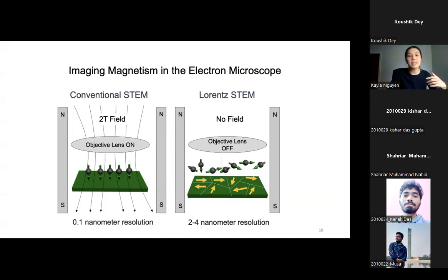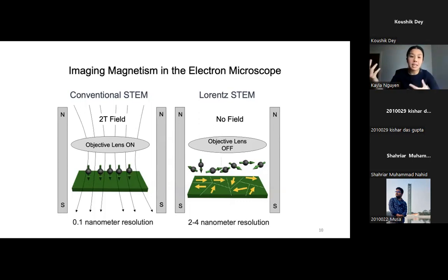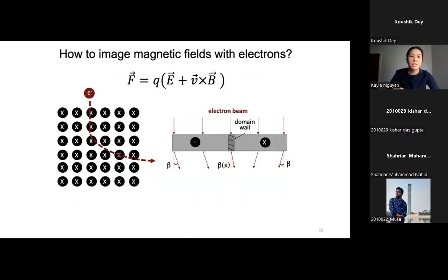The issue with this is that with the objective lens on, you have a very focused probe that gives you 1 angstrom or 0.1 nanometer resolution. By turning off the objective lens, your resolution then becomes 2 to 4 nanometers. But that's fine because the magnetic structures that we're looking at are about 50 nanometers. Okay, so that's one thing you need to do: make sure you turn off your objective lens so that you're not applying a field to the sample and the spins of your sample are not aligned to the field of the microscope. The second part is how do you actually look at or image fields with electrons?